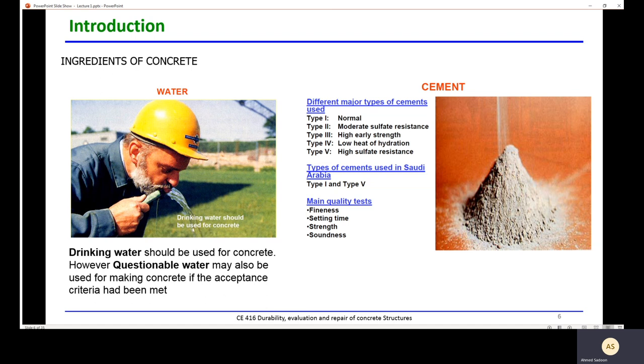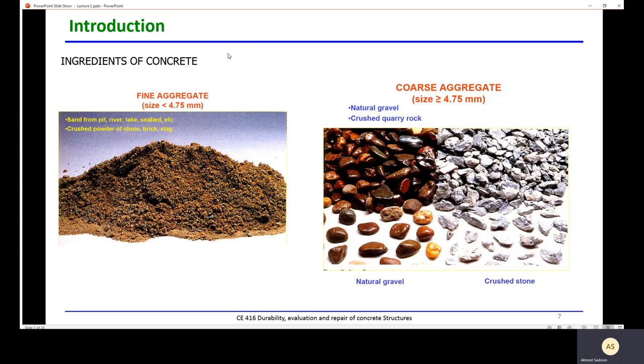We also need to take care of cement quality properties: fineness, setting time, strength, and soundness. Setting time is very important — defined by initial and final setting time. The initial setting time may be between two to three hours. Before the initial setting time, you should finish delivering, casting, and compacting the concrete, because after the initial setting time dealing with the concrete becomes very difficult.